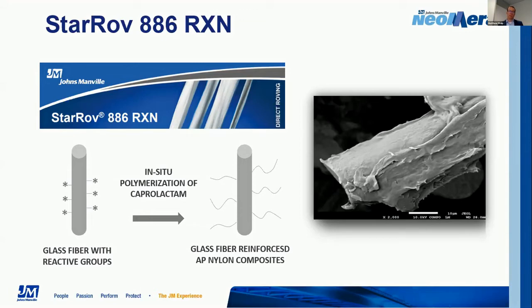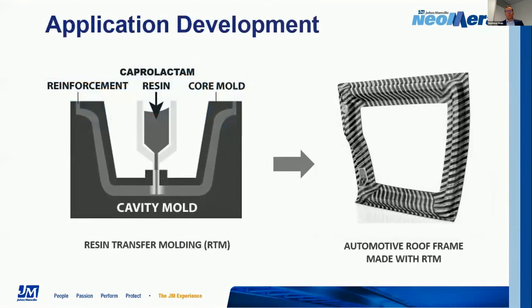And as you can see in some SEM photos, you end up getting a very strong interface. And so you don't get the sort of interfacial failure you might see in other materials. So this was mainly designed for the RTM industry. That caprolactam based system, you've got some sort of reinforcement, and then you've got the resin system. Those are mixed inside of a mold, and you get the polymerization inside the mold itself, and then you get your part that comes out of the mold. It's a very interesting process.